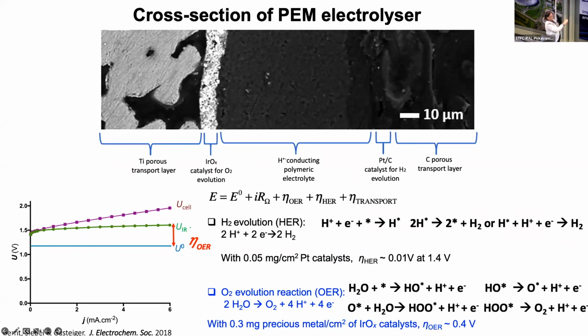And then you see the Nafion in between. Is there a pointer? Yes. Sorry. There's the Nafion membrane here. And then here is the hydrogen evolution side. So you have platinum supported on carbon, and then you have a carbon transport layer, because here you don't work under such negative potentials for this reaction.